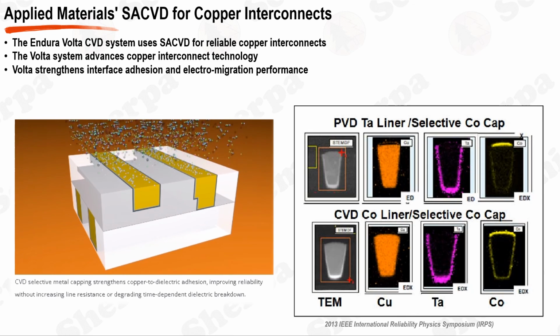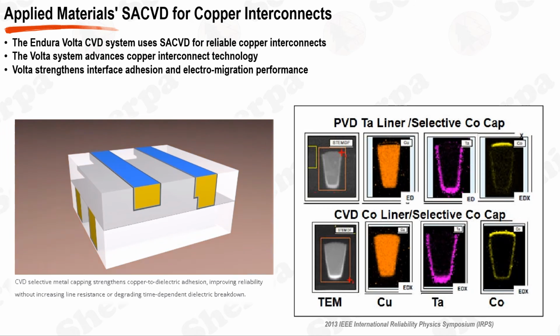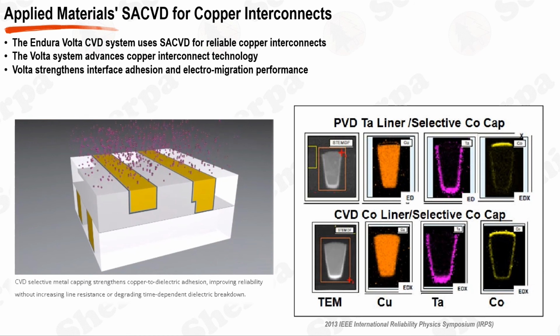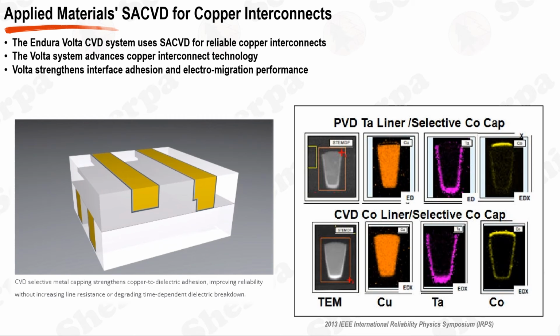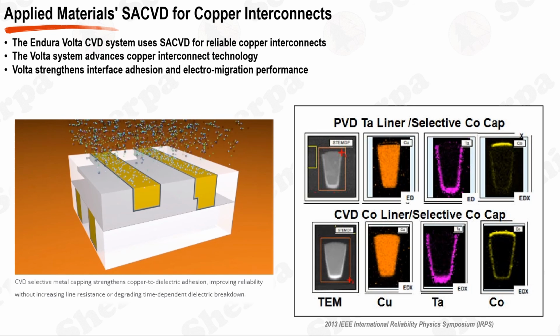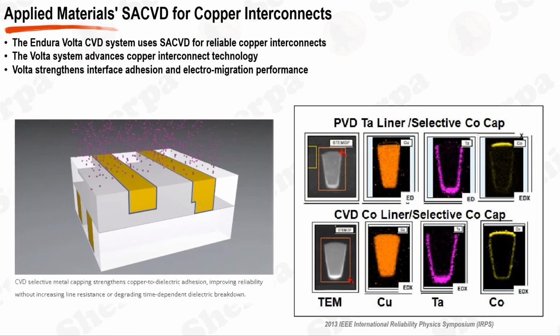One of the prime applications of SACVD can be observed in the fabrication process of Applied Materials' Endura Volta CVD cobalt system, which encapsulates copper interconnects with a thin, conformal CVD cobalt layer, enhancing reliability and scalability beyond the 2x nanometer node. Applied Materials technology represents a significant shift in the copper barrier/seed (CUBS) development, introducing the first material alteration in more than 15 years.